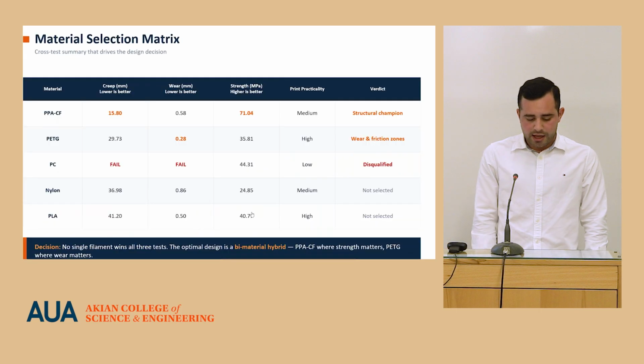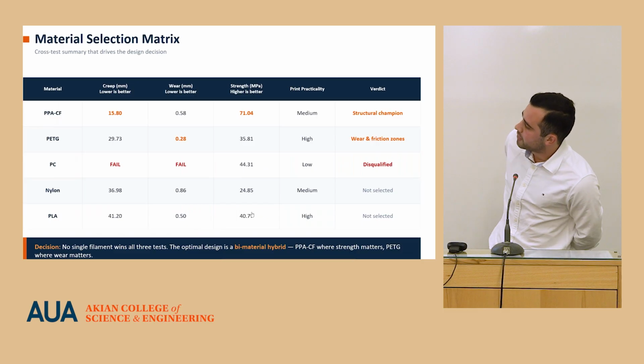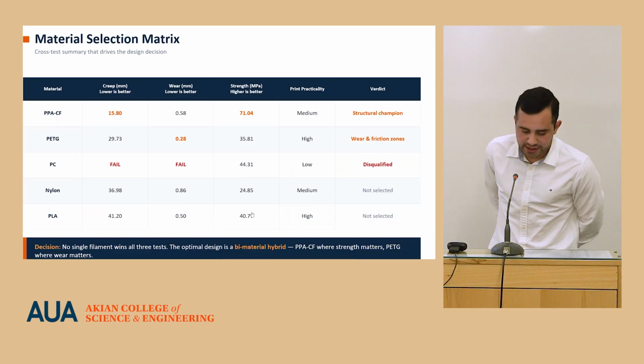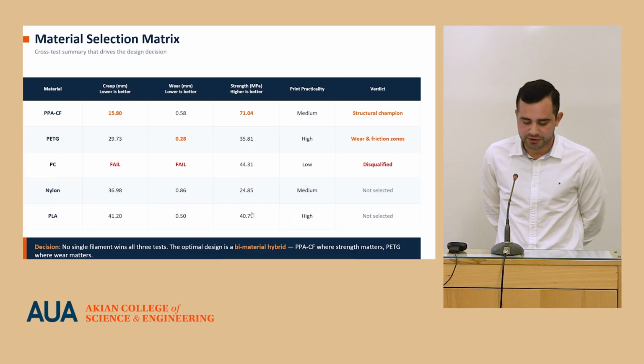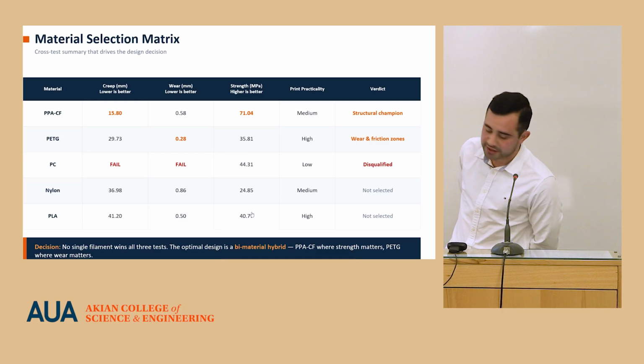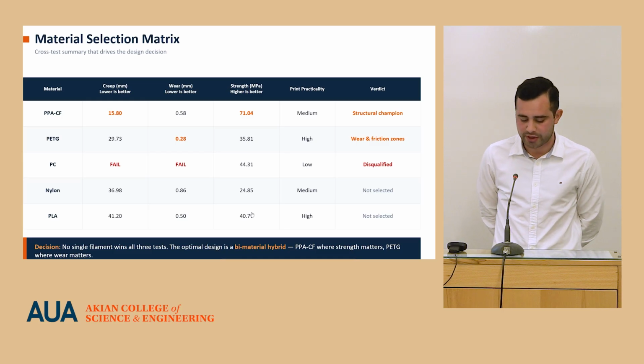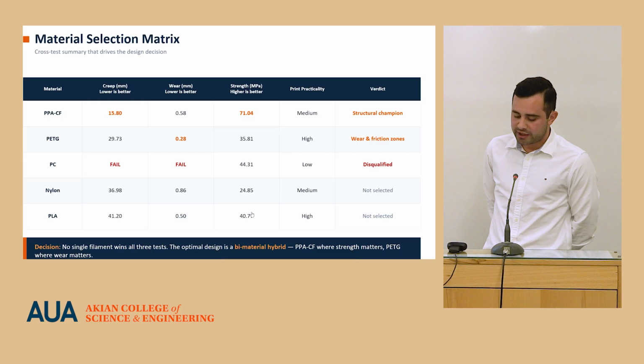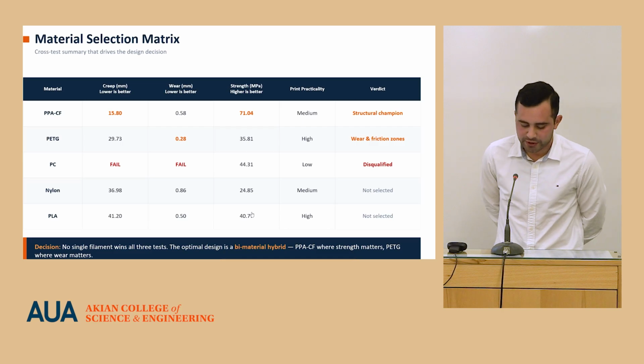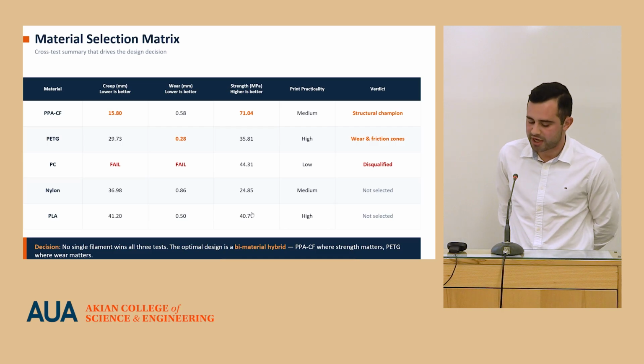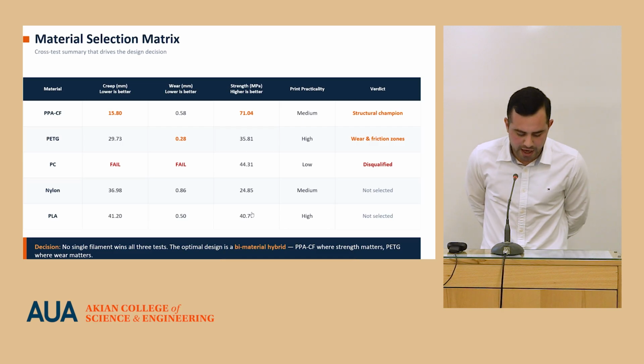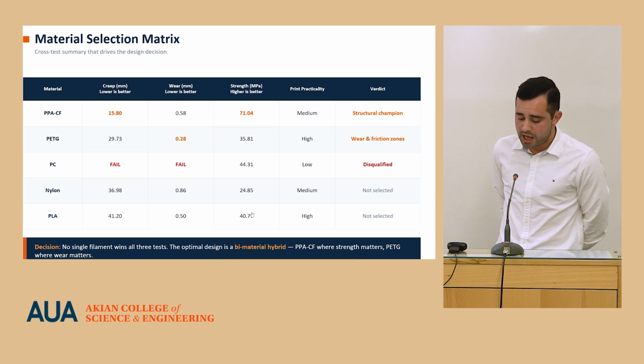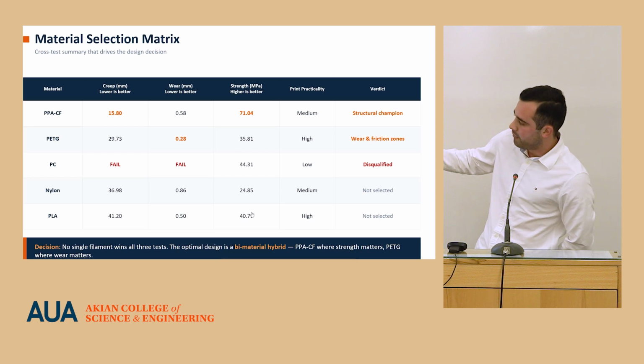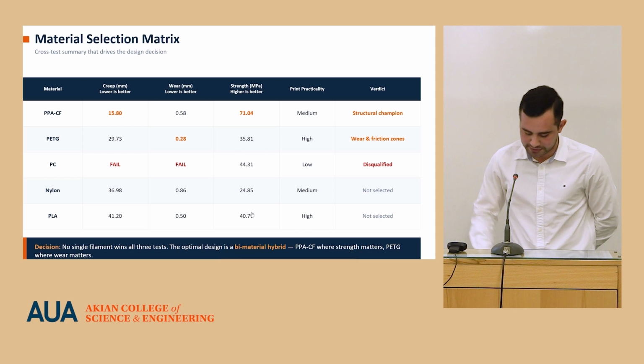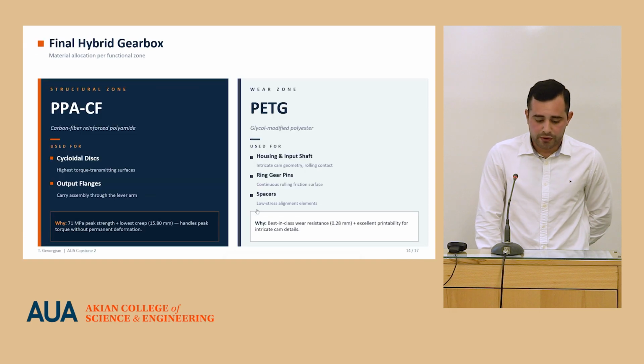So here are all the results from all the tests that I've conducted. You can see that carbon fiber was a winner at the creep test and tensile test, and PETG was the winner at the wear test. Polycarbonate was disqualified because it failed 2 tests and was average in the third one, and nylon and PLA were not selected because they were average in each test.